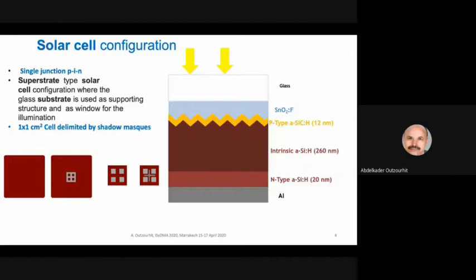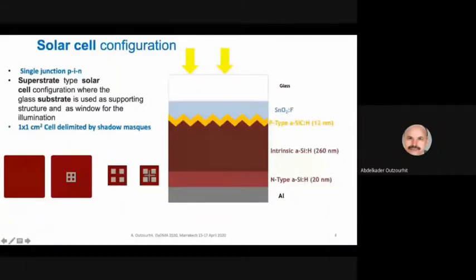Finally, this is completed by an aluminum ohmic contact or back contact, which acts also as a reflector that aids in trapping the light by reflection in the cells, thus maximizing the absorption of the light within the cell, since it is a very thin film solar cell. So the light trapping is also due to the texture of the upper layers here, where the multiple reflections from the facets of this texture aid also in keeping the light inside the cell, thus increasing the absorption and consequently the efficiency of the cell.